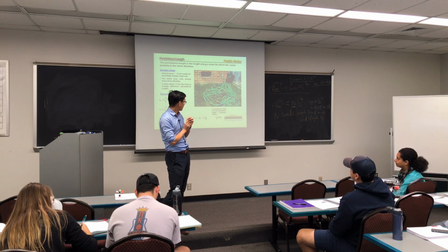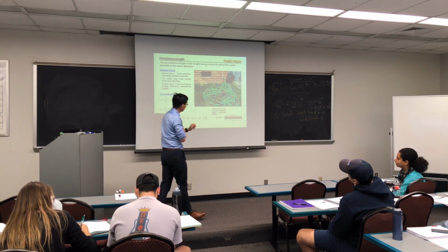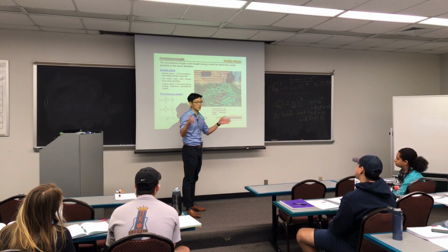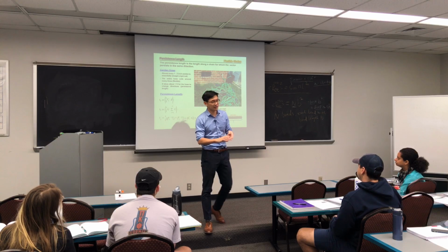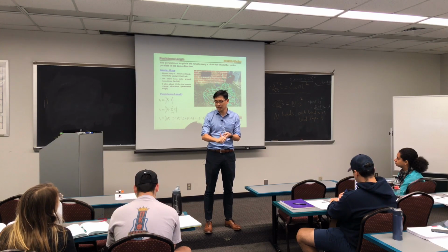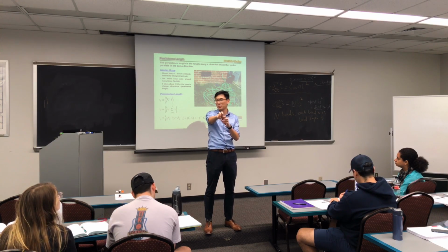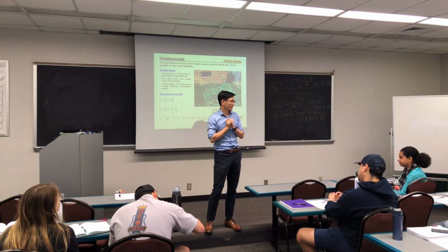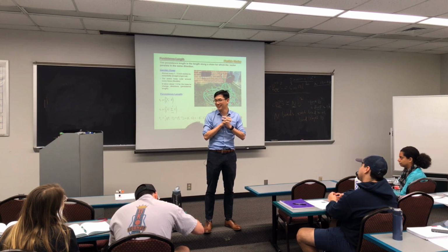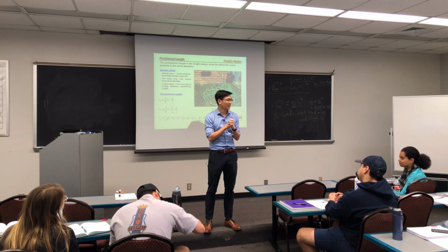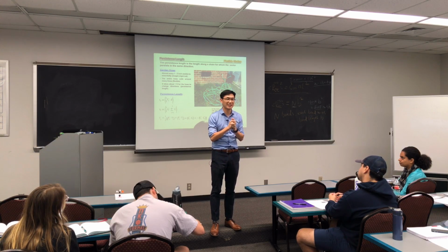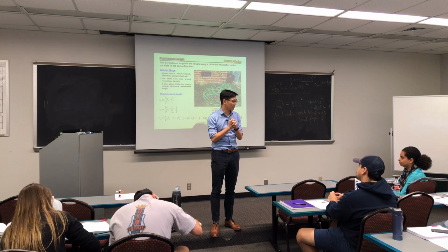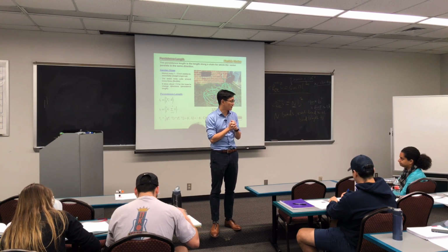So what the physical meaning is, you have to compare the persistence length versus its contour length, or how long your molecule you are trying to compare. I'll give you three scenarios. If your persistence length, or how much long chain remembers direction, is much larger than its contour length, is the polymer rigid or soft? Super rigid, right? If they're on a similar order of value, let's say your persistence length is similar in length as contour length, then we actually call it semi-rigid.